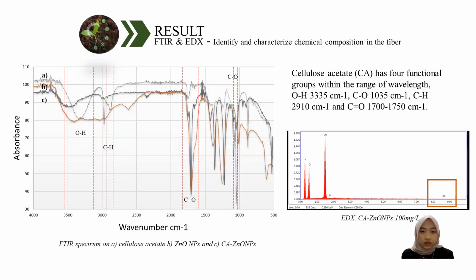As for the FTIR and EDX studies, they are to study the presence of zinc and also cellulose acetate within the fiber. Cellulose acetate has functional groups, which are O-H, C-O, C-H and C=O. And as we can see here, with the available peaks and wavelengths in the FTIR results, that's the presence of cellulose acetate. And the zinc oxide nanoparticles bond with the C=O here. So we can see the high absorption and high stretching peak of C=O. This indicates the presence of zinc oxide. For the EDX study also, we are able to see the presence of zinc oxide nanoparticles.